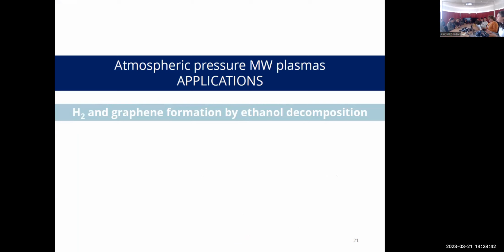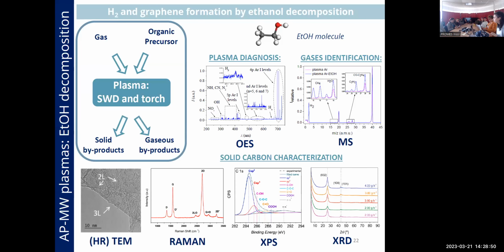Okay, so now that I have tried to summarize very briefly the fundamentals of our devices and our discharges, let's move on to see if it's possible to produce hydrogen and two-dimensional carbon, solid carbon. So what is the idea? We have a main carrier gas, which will be argon. Then we have an organic precursor that will be ethanol. We are going to introduce the ethanol together with the gas into our surface wave discharge, sustained with the surfatron, and also our discharge created with our Tiago torch.